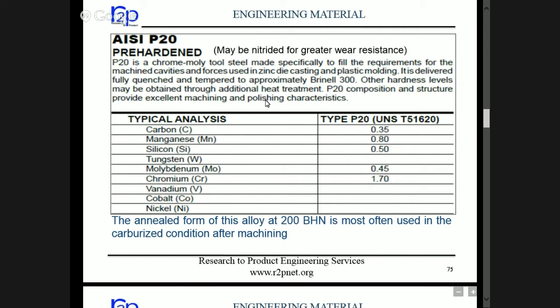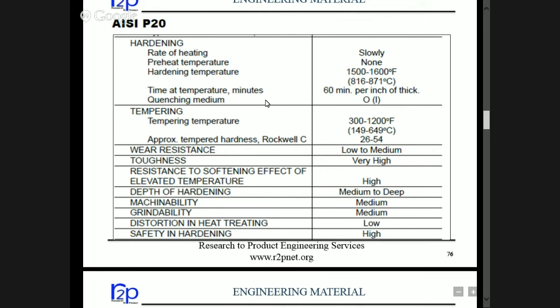Because in the case of die casting, whether aluminum or plastic injection molding, the pressures are there, but the impact is not there. The plunger which creates the pressure for injection molding or aluminum die casting moves slowly. If the pressures are there, there is no impact. So a non-heat-treated, only nitrided die can be used in P20. Similarly, hardening temperatures and tempering temperatures are given.